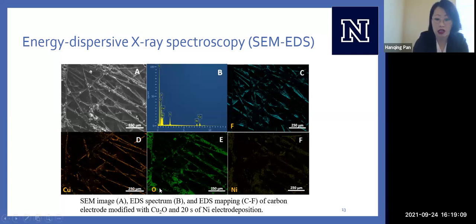We see copper and oxygen and nickel, and they indeed are only preferentially depositing along the fibers and the spindles of our carbon paper. The carbon paper spindles are kind of serving as nucleation sites for our catalyst to grow. And this makes sense because it's impossible to deposit in these empty spaces.